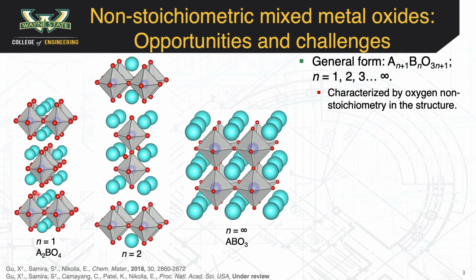When n equal to 1, a typical layered structure called the Ruddlesden-Popper phase is formed, where a perovskite layer is separated by a rock salt layer, and the perovskite and the rock salt layer continue on in the z direction. As one moves towards n equal to infinity, a typical perovskite type structure is formed that I am sure most of you have heard about. These oxides are mixed ionic and electronic conducting in nature, thus making them suitable for electrocatalytic applications.